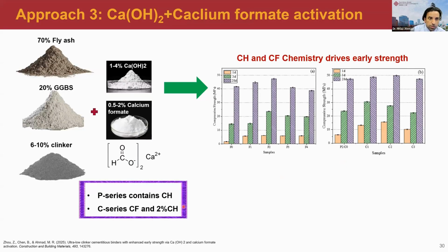One is a P series, which only contains CH. The other was a mixture which contains the calcium formate and CH. So first we optimize the percentage of the calcium hydroxide, or CH, and we observed that we can achieve around 4.8 megapascal by using this 2% CH.